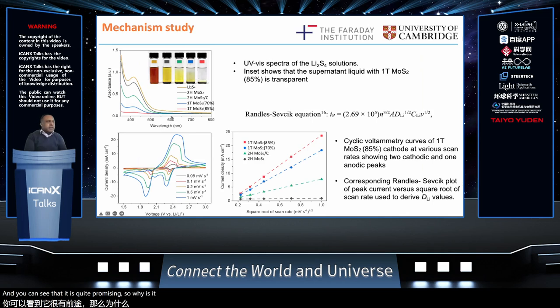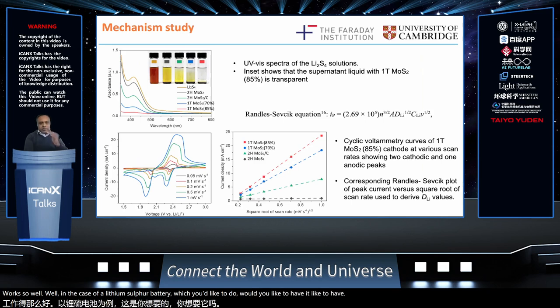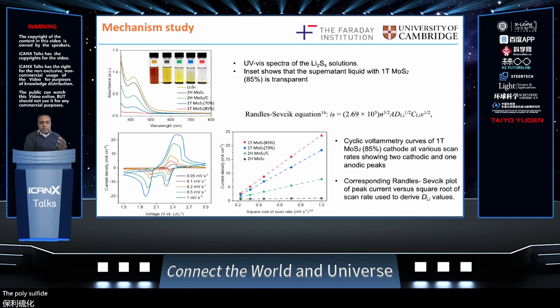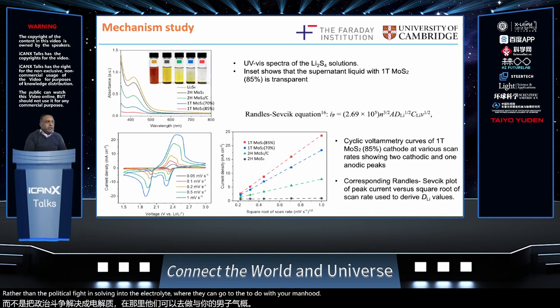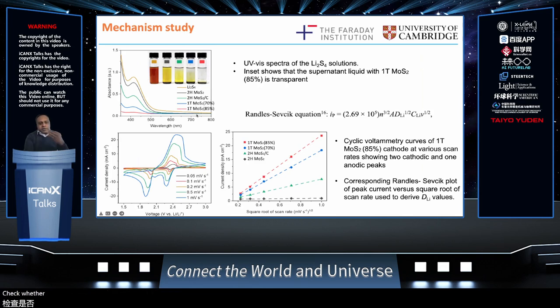So why is it that MoS2 works so well? Well, in the case of lithium sulfur battery, what you'd like to have is the sulfur adsorbed onto your cathode scaffold, in this case, 1T MoS2. You'd like to have the polysulfide or the sulfur reduction reaction happen on the cathode rather than the polysulfide dissolving into the electrolyte, where they can go to the lithium anode and destroy the capacity. And so the way to check whether the sulfur remains adsorbed onto the scaffold is to look at the adsorption capability of the different polysulfides onto the different cathode materials.